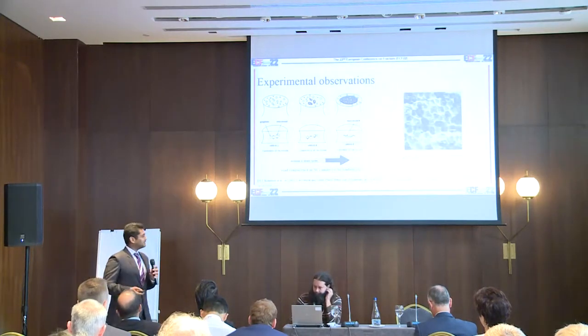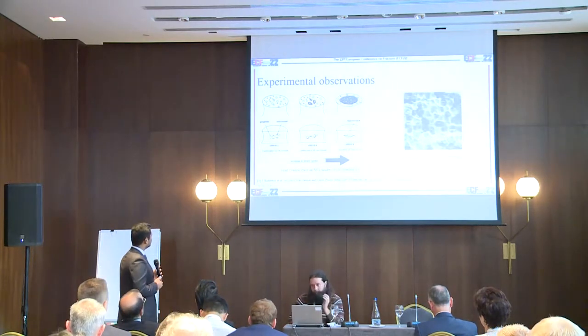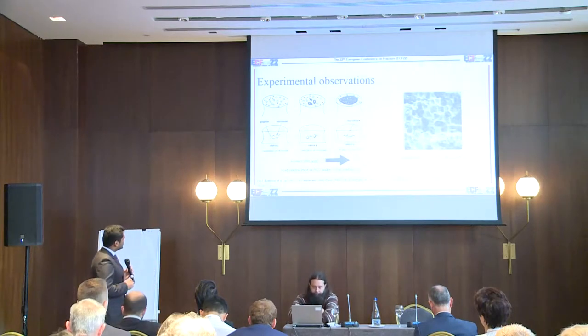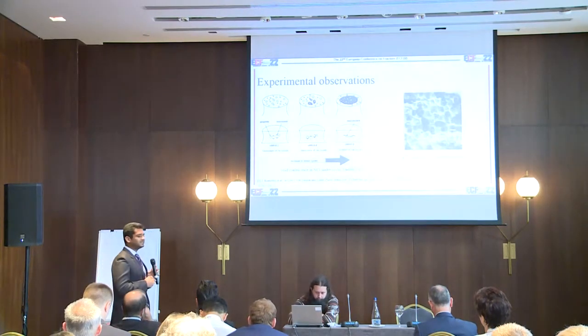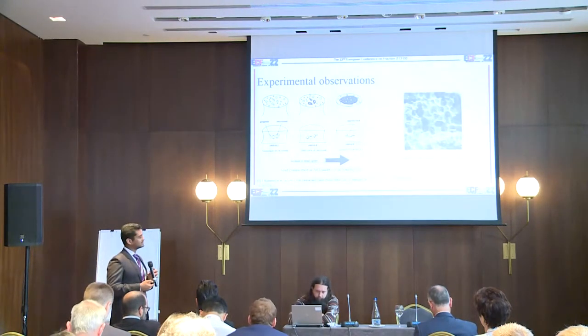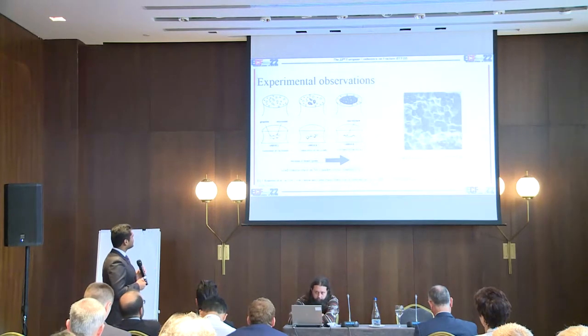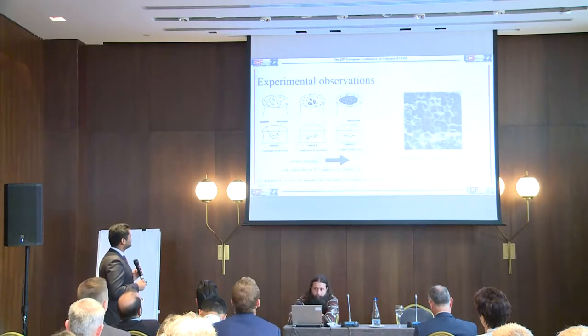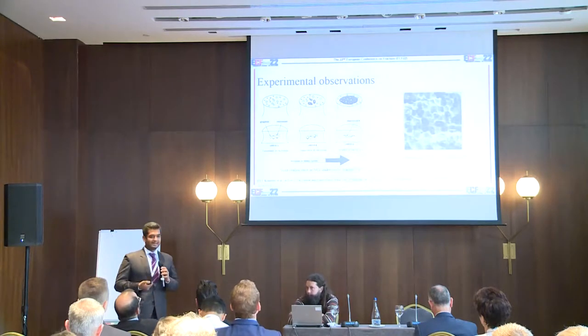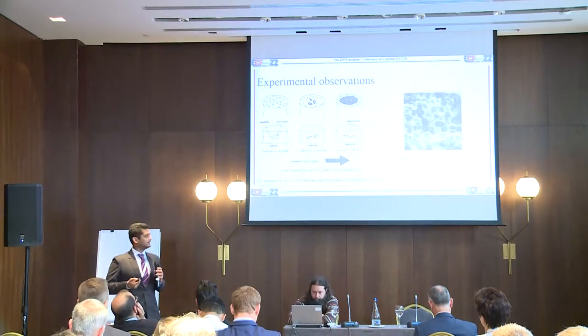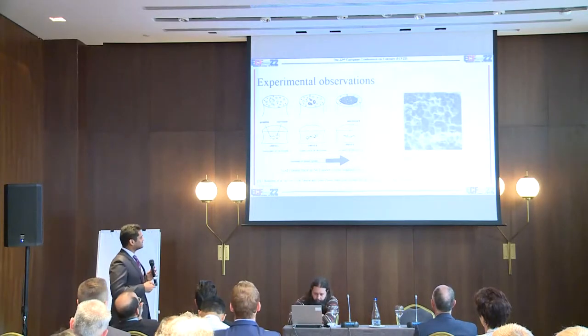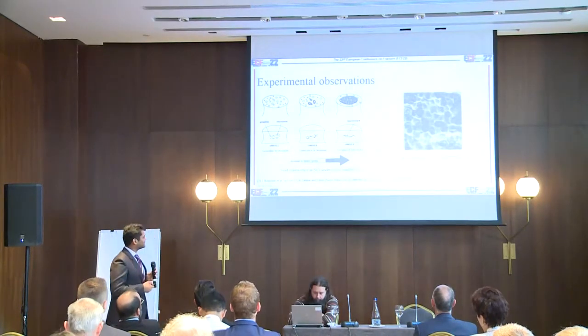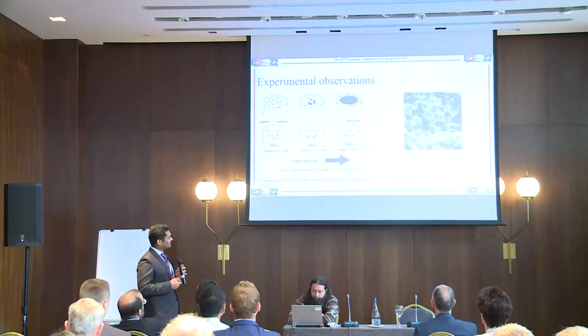This debonding leads to generation of micro-voids. As we increase the number of cycles, we see that initially there is generation of micro-voids, and as the experiment progresses, these micro-voids are increasing and growing in size. After some time, they coalesce and form a microscopic crack. A similar observation was also found by our colleagues, Thomas Mortiske et al., at TU Bergakademie Freiberg.